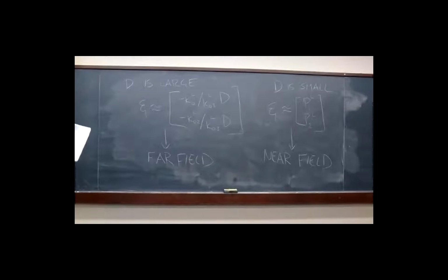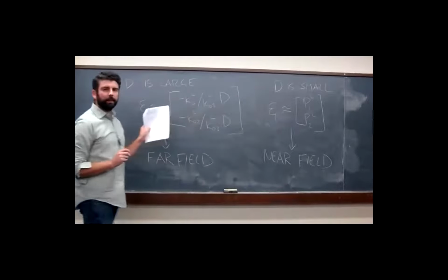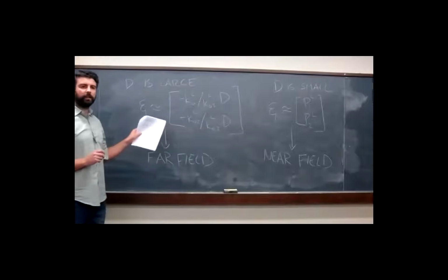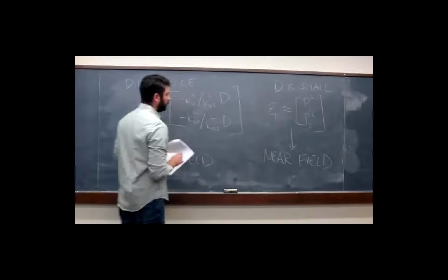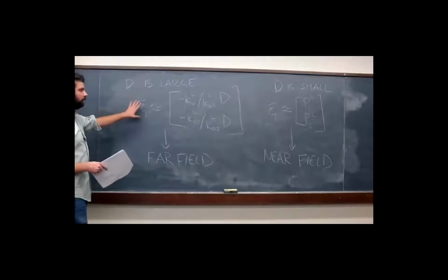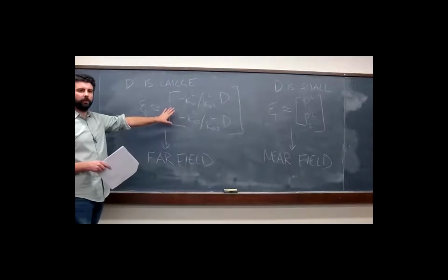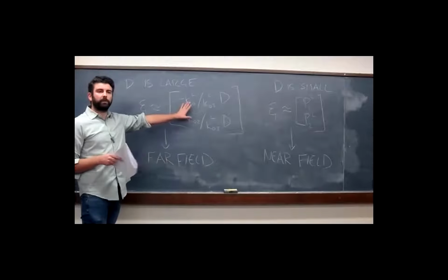The important point I want to make is that no matter where you put the detector, there's always going to be some small effects of both. Even if you're in the near field, the direction of the diffracted intensity will show up, but it will be a small influence on where you measure intensity on the detector. And if you're in the far field, you're still going to get small influences from the position of the crystal, but the position is going to be mostly dominated by the direction at which diffracted intensity is emitted onto the detector. And I'll have some graphics showing that in a little bit.